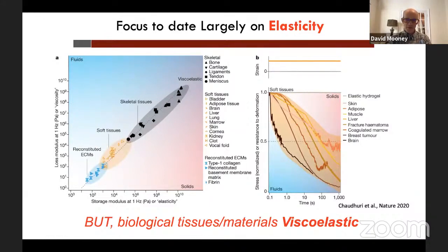Another way one can actually monitor viscoelastic properties is shown on the right, where if one takes a material and places it under a constant strain, one can measure the amount of stress that's required to maintain that deformation. If one has an elastic material like a rubber band, the actual stress will stay constant with time. So the line along the top here. In contrast, if one looks at tissues in our body, they actually dissipate the stresses over time. So the amount of stress actually is diminished. So these materials in our body, the normal extracellular matrices, are actually viscoelastic. And so that led to the question starting a few years ago: do cells then actually read and care about the viscoelastic properties, or is it really just the stiffness that matters?